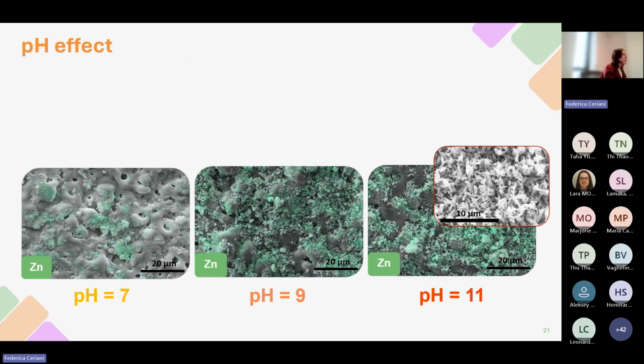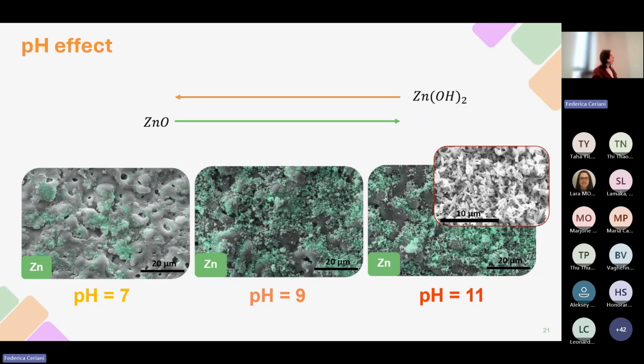Indeed, we have said that for increasing pH, the quantity of zinc hydroxide that is present on the surface of the sealed coating decreases, and on the other hand, the quantity of zinc oxide that is present increases. And zinc oxide is characterized by a petal-like shaped structure that is exactly the one observed for the most alkaline sealing bath. Another phenomenon that we have to take into account is the fact that for pH equal to 7 or even lower, the partial dissolution of the zinc-containing precipitates as well as of magnesium hydroxide structure could take place. And this explains why, in the case of the most acidic solution, the one with a pH equal to 7, precipitates are almost completely absent.